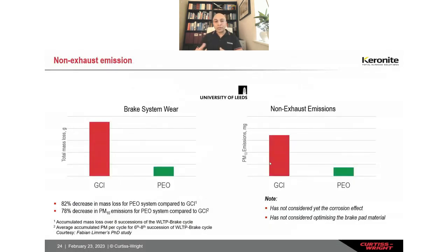Now, let's have a look at the non-exhaust emissions. We have been doing this test for a number of years. Leeds University has an extensive, state-of-the-art facility for measuring brake disc particle emissions. This particular data was donated by our student, Fabian Limmer, who's in the last year of his PhD. As you can see, the total mass loss from the grey cast iron system is over here, and the PEO coated shows about an 82% reduction in mass loss. On the right-hand side of this plot are the non-exhaust emissions, especially the PM10 emissions. Again, PEO coated shows a 78% decrease in PM emissions, and that is incredibly encouraging data.